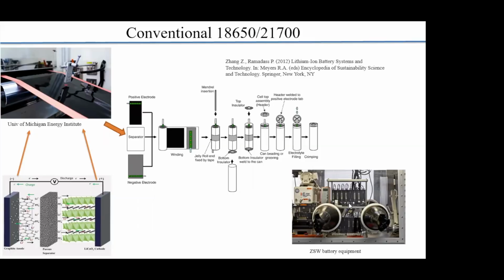Basically the cell goes into an inert atmosphere, a glove box atmosphere, and then you see the cells here, right? They're filled with electrolytes, and then they seal it, and then that goes into testing. So this is the step, right, from preparing the slurry of electrodes to putting it on the current collector, making it into a jelly roll. Once you have the jelly roll, you have this top cap before you close the seal. You put in the electrolyte, and then you have an 18650 or 21700 cell.